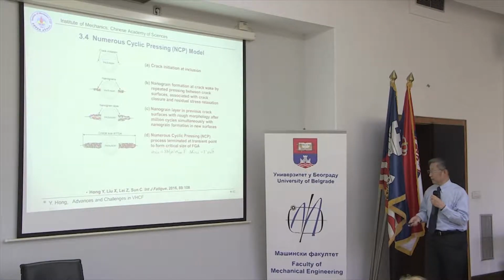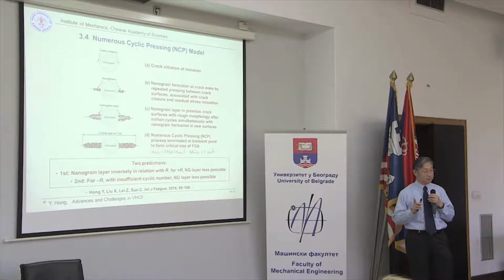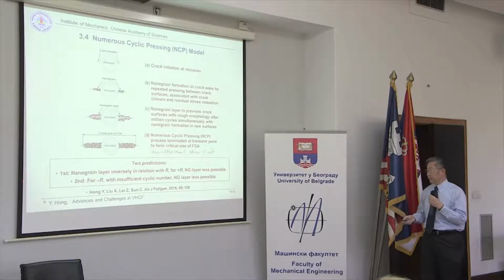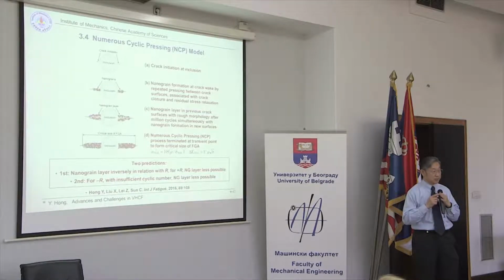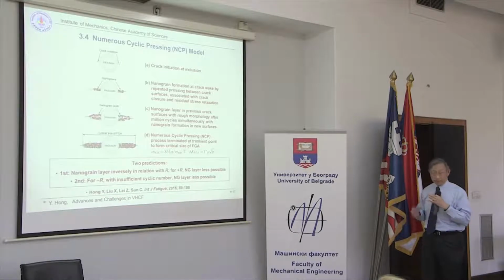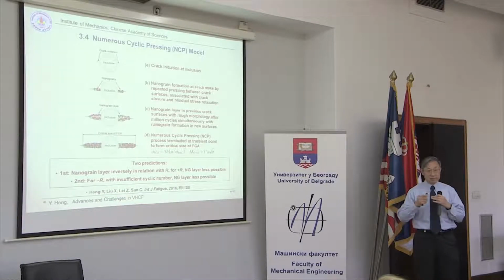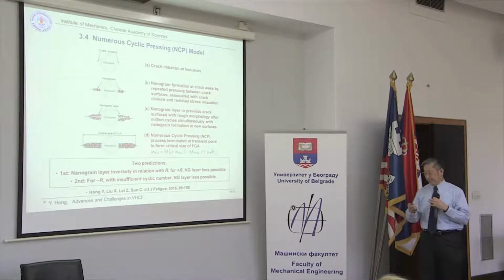And then we may have two predictions based on this model. The first is that for positive stress ratios, this type of nanograin layer could be less possible. And the second one is that even for negative stress ratio, if the loading cycle is insufficient, this type of morphology will be less possible, because this type of feature is in relation to the contact of crack surfaces.